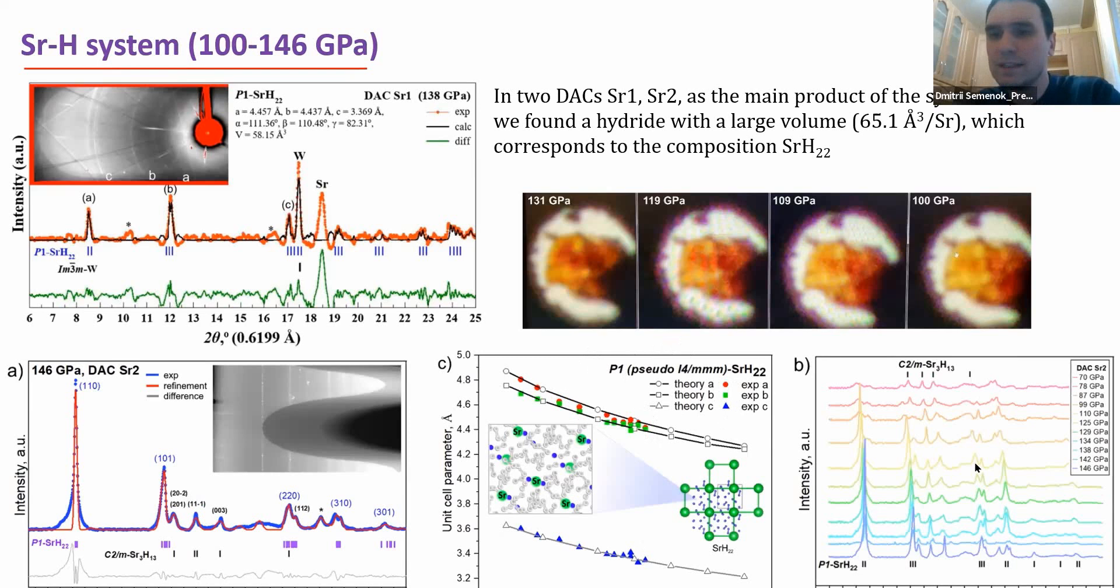We decompressed the cell, decreased the pressure and found that actually the diffraction peaks from strontium H22 disappear at about 90-95 GPa. We see in the remaining pattern only impurity, only three or four diffraction peaks from impurity from strontium H13. These are pictures from samples from diamond anvil cell. This is exactly the cleanest sample of strontium H22. You see it's a yellow compound, yellow semiconductor which significantly darkens when we increase the pressure, which corresponds to gradual metallization of this compound and decreasing the band gap in the semiconductor.